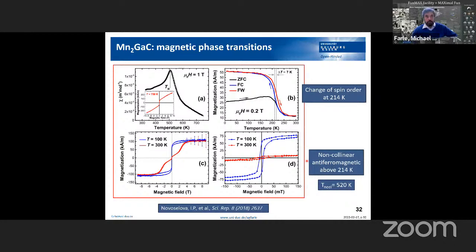First, let's look at the magnetic characterization. Here we have the susceptibility at high temperatures, above room temperature. We know from other measurements that in this range it's antiferromagnetic, and then here we have a somewhat complicated Curie-Weiss behavior. In this range, above roughly 500 Kelvin, it's paramagnetic or superparamagnetic. So there are a lot of open questions still. You see here at 750 Kelvin, we have this funny